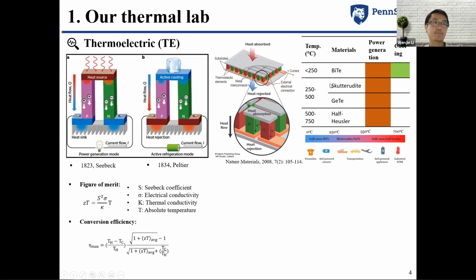Skutterudite shows very good performance for the N-type, and germanium telluride has a big advantage for the P-type materials. And for the higher temperature range up to 750 degrees C, we have this rising star of half-Heusler materials, which shows excellent ZT performance as well as good mechanical properties. For the medium to high temperature thermoelectric materials, we are only focused on power generation.